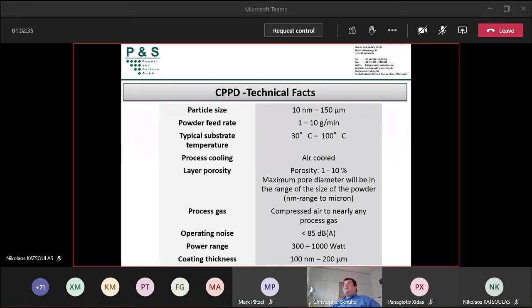The next thing is the typical substrate temperature. That's the main point. We can go from 30 degrees up to 100 degrees and melt on the thermoplastic, for example, a little bit, but without the thermal destroy of the substrate. So you saw this in the last presentation from Trace or from ITER, the shrink in the fabrics. You can avoid this with this technology. You don't heat up the substrate so much to plastify it and to implant the particles inside.